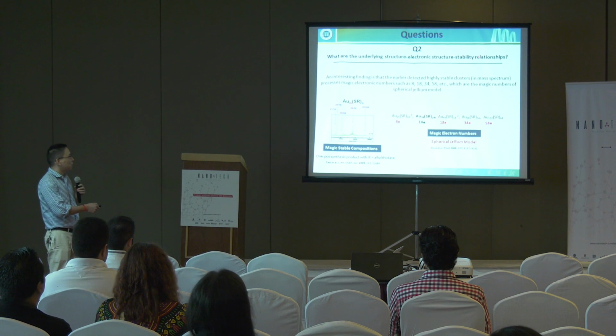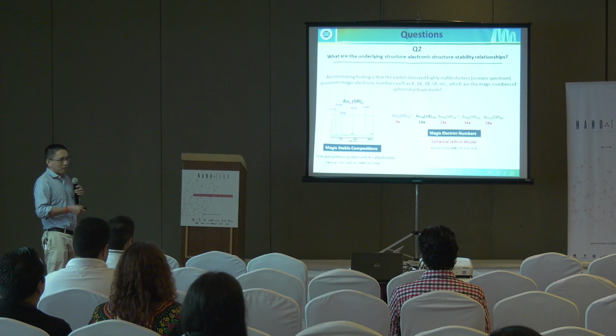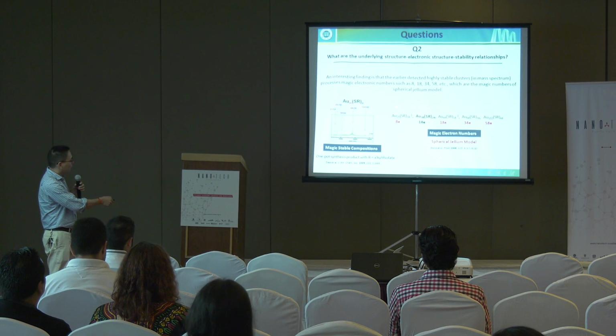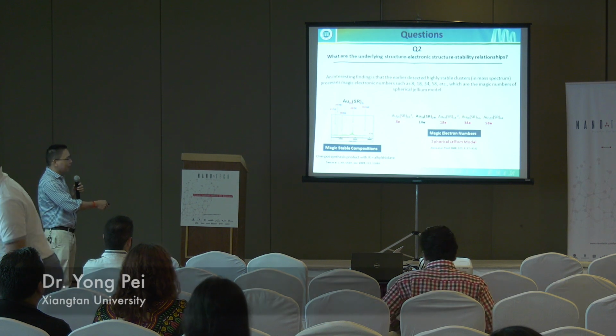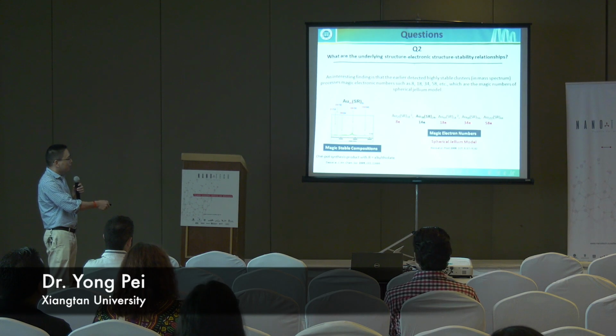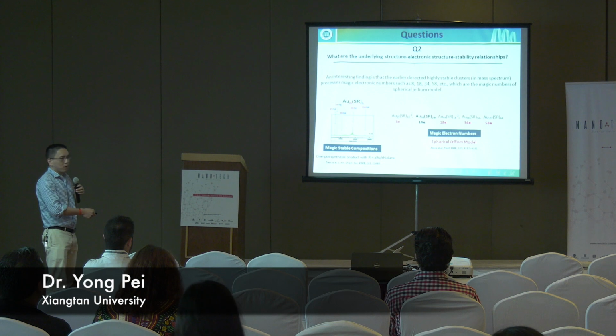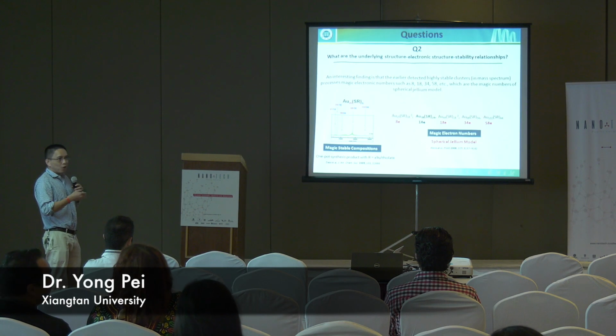And for the second question, what is the underlying structure, electronic structure, stability relationship for these clusters? Why this question? Because from this mass spectrum, people have found in the one-pot synthesis, some clusters exhibited exceptional stabilities. For instance, these clusters are very stable during the one-pot synthesis in solution. If we count the electron numbers of these clusters, for example, this one has 8 electrons. This one has 18 electrons, and 34, 58. We know these red electron numbers are the magic numbers in the spherical jellium model. So this can be used to explain their stabilities.